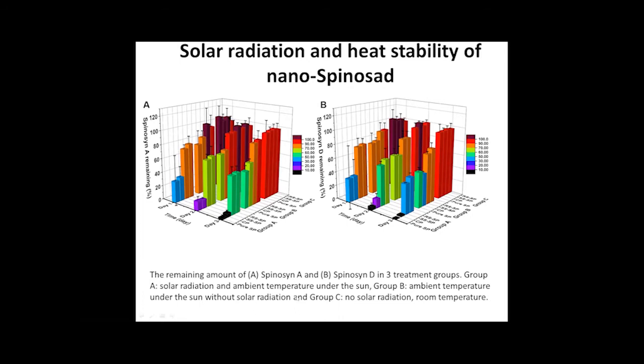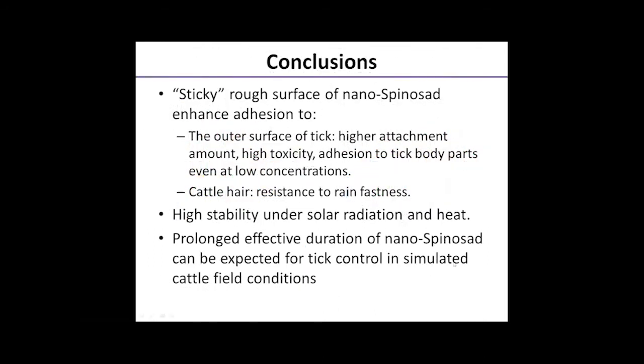These results show the silica nanocarrier indeed plays a role as a UV shield to provide heat and photodegradation protection for biopesticide molecules. As a conclusion of this work, I have developed a nanospinosad formulation with a sticky rough surface with dual adhesion efficacy to cattle hide and parasite body. The dual adhesion property leads to significantly higher pest mortality towards tick as the pest than a nanospinosad formulation using nanoparticle with the smooth surface and the benchmark commercial product.